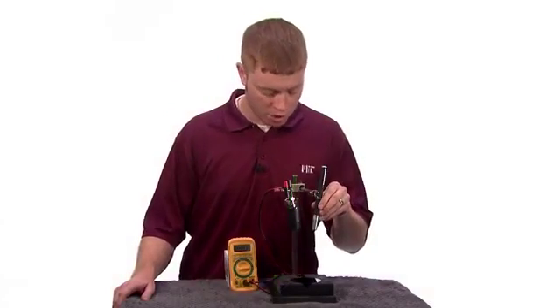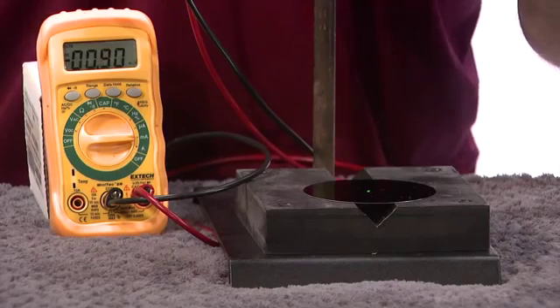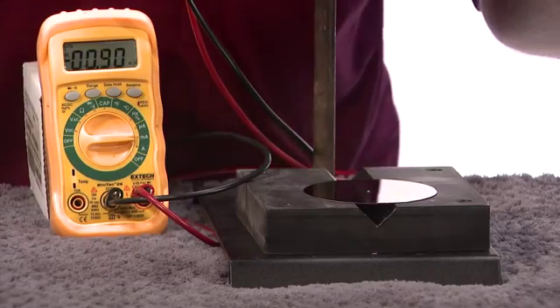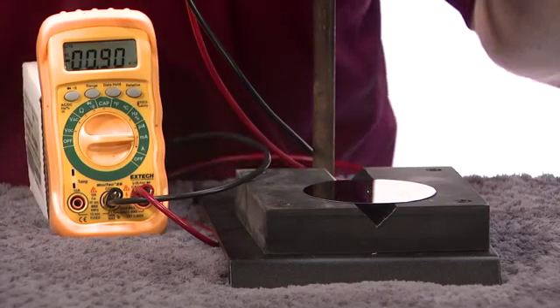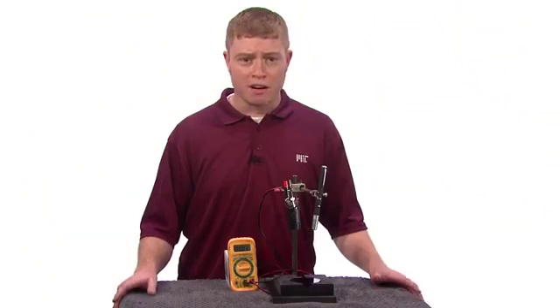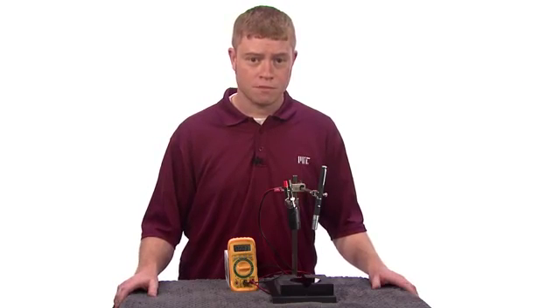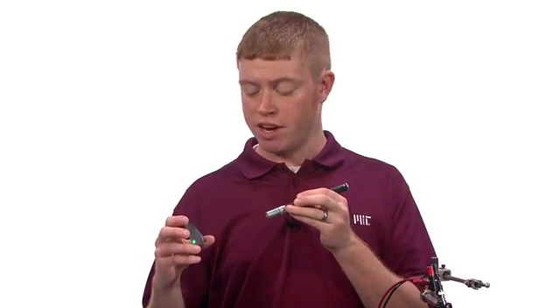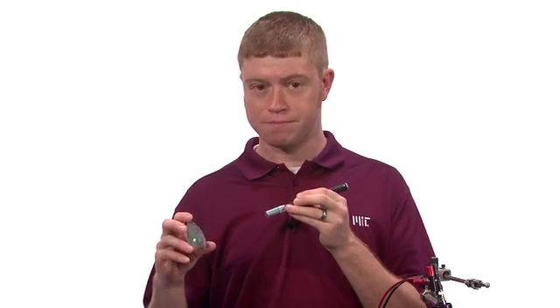Now, if we turn on our laser pointer, it hits our photodiode, and we can get a good reading. And right now, we see that it's reading around 0.9 milliamps. But how does this compare to a textured wafer? Let's find out. Now, it's hard to measure the reflectivity of a textured wafer with a laser pointer because it bounces the light off at several different angles. And we can't measure the entire beam with a photodiode alone. However, we can simulate what this would be like. Let's go to our sketchboard to show how we can approximate this measurement.